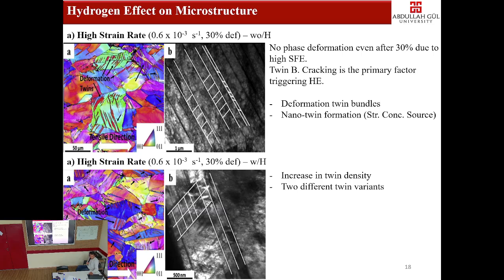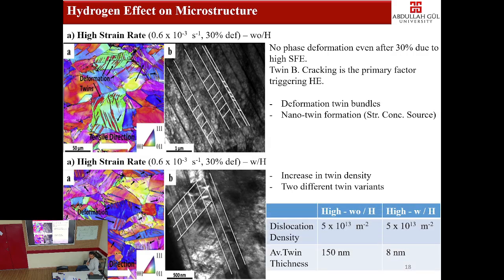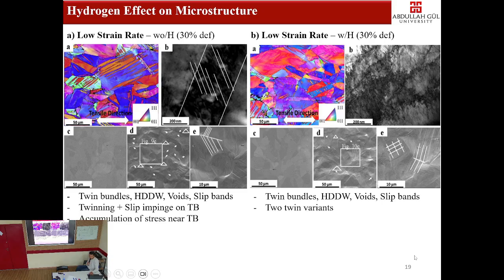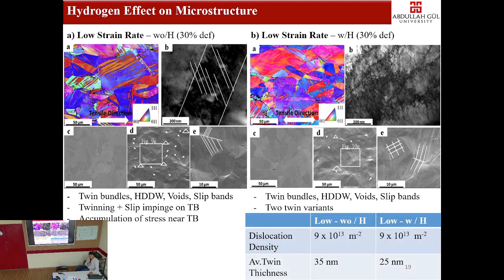These are the EBSD maps after 30% of deformation. We saw some nano-twins, two different twin systems, without hydrogen and with hydrogen. So hydrogen increased the microstructural features. We measured the dislocation density and the average twin thickness. Of course, if it's lower, there is much more hardening. So here we have 30% deformation in situ in the SEM. We did the tensile test inside the SEM chamber. These are the slip bands at 30% of deformation with and without hydrogen.